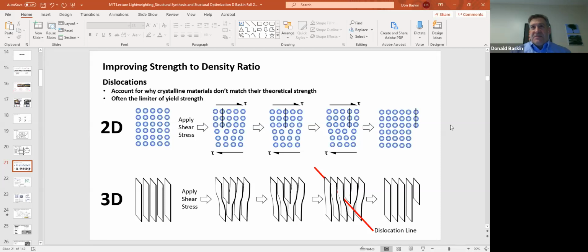If you're a physicist or a material scientist who's very fundamentally minded, and you try to calculate the strength of a given metal based on the attraction between the atoms in the crystalline lattice, you will come up with a strength that is much, much higher than what you get out of real materials. Remember I said back in the 50s, when people focused on understanding why properties existed, they went from the right to the left along those three links. They discovered these dislocations, and that became the fundamental theory for why real metals were weaker than the attraction between the atoms would suggest.